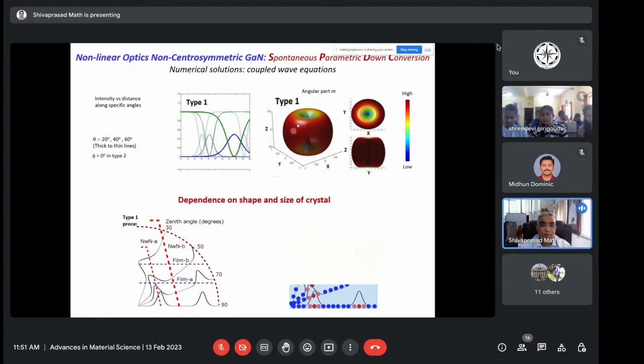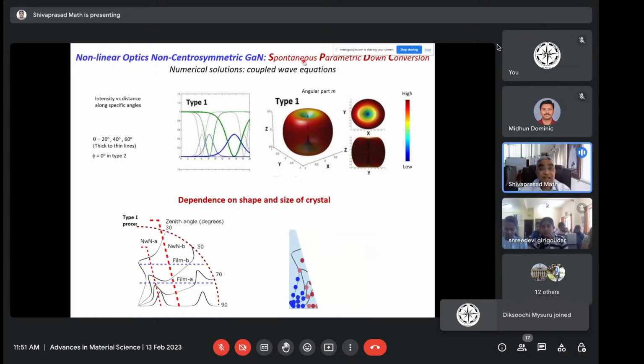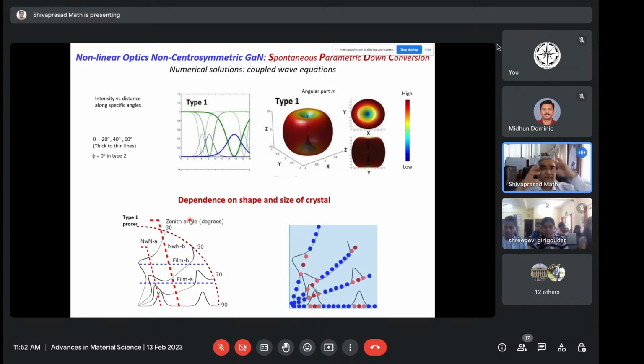Very interestingly, we saw evidence for a spontaneous parametric down conversion. That means the photon of light which was traveling in this material, because this is a non-centrosymmetric material. That means it has a built-in electric field inside that material, gallium nitride, because there is not equal distribution of gallium and nitrogen charges. So there is a built-in field inside that. So when this light passes through, it actually breaks up that photon into two photons. And that is what we call spontaneous parametric down conversion. So that's what was happening in this case. And we did that calculation, which also showed that it is possible.